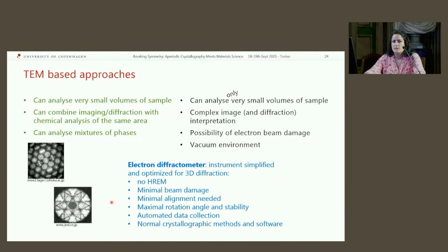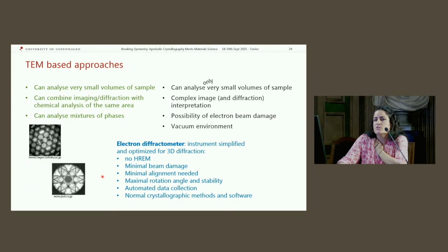But recently we have seen the appearance on the market of electron diffractometers, which are still based on an electron beam and electromagnetic lenses, but they are optimized for diffraction. So we cannot zoom in and see the atoms with high resolution, but we can collect as complete a data set of diffraction patterns as possible, and these are optimized so that we need only low illumination, so we minimize beam damage, and we can analyze many kinds of samples, from minerals to intermetallics, to organics, and to proteins. And we use the methods and software that we normally use for X-ray crystallography.